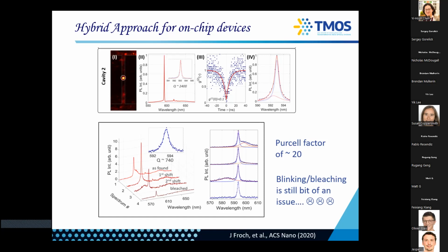So this is basically as found an emitter, the cavity mode is here and the emitter is this broad thing. This is a random shift. You see it's coupled perfectly. Then the emitter goes to the other side and then it bleached out. So that's still the cavity mode. So we don't really know how to solve it just yet.